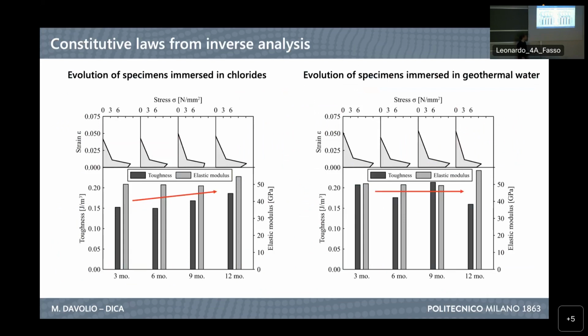Then, these are the results from the last step I mentioned. I am just presenting two cases, which are the specimens immersed in chlorides and in geothermal water, because what we observed from crack sealing is that for the chlorides, we had this phenomenon of remarkable sealing of the cracks at very short times, which is confirmed by the inverse analysis with this increase of the toughness of the material, while geothermal water performed almost constant over time with some scattering from the first period to the last one. And this is where we experience some reduction of the response of the